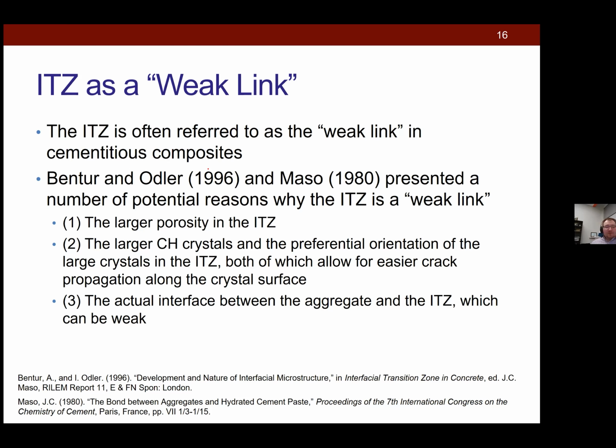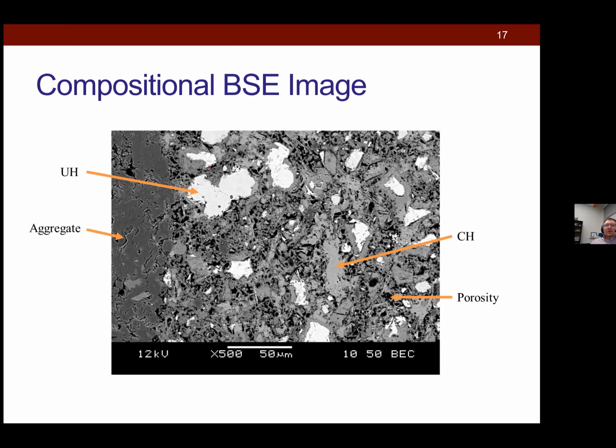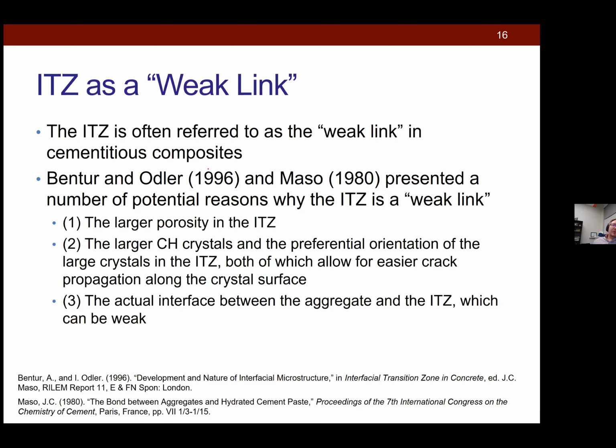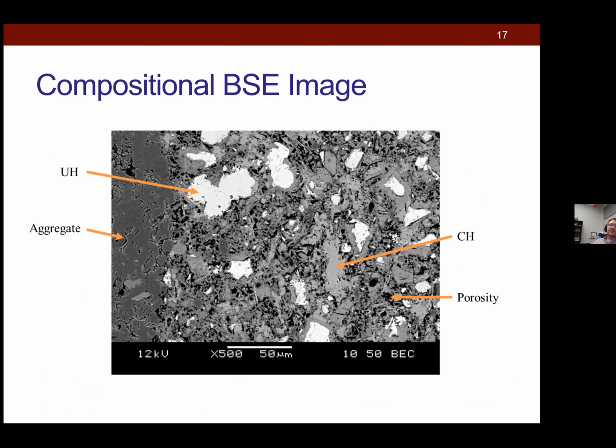Okay. So if you look at a lot of the historical perspectives on that interfacial transition zone, the ITZ, that's the zone around the aggregates that basically forms due to packing inefficiencies. ITZ has a higher porosity. So now you have a larger volume of a lower modulus phase essentially in your bulk concrete. You have these larger calcium hydroxide crystals, which some argued would allow for easier crack propagation. And then we have the actual chemical or physicochemical bond between the cement paste and the aggregate surface. So what I did was pretty much looking at one and three, which were really the focus of my PhD.